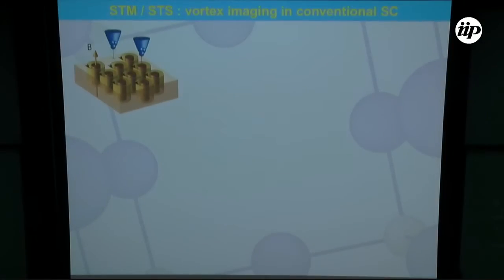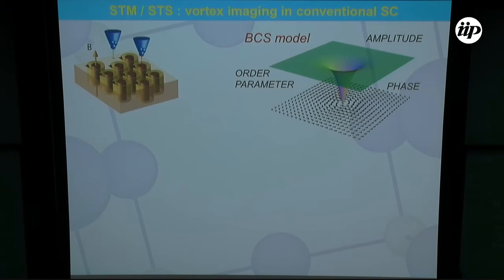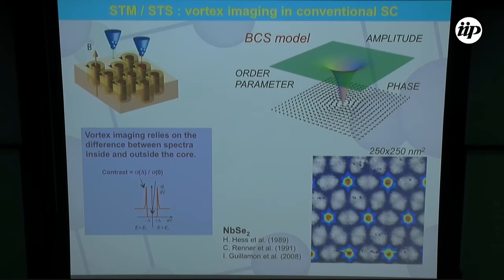Okay, so, rapidly, scanning tunneling spectroscopy on vortices. You know, of course, a vortex is a singularity in the order parameter, and what is expected is that when you acquire spectra outside or inside the vortex cores, they should be different, and you just exploit the difference in the conductance outside and inside the vortices to make a spectroscopic map of the vortices. This is clear. This is niobium diselenide, but what about the spectroscopic signature of the core?